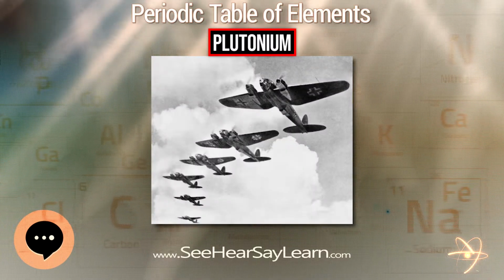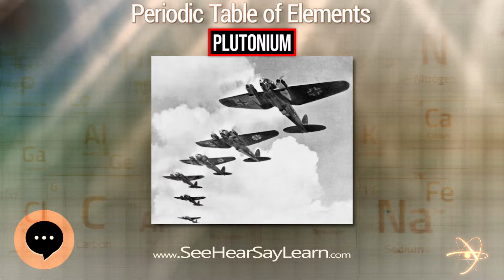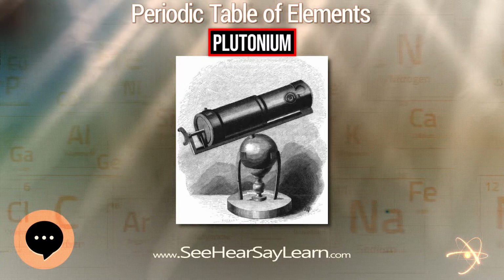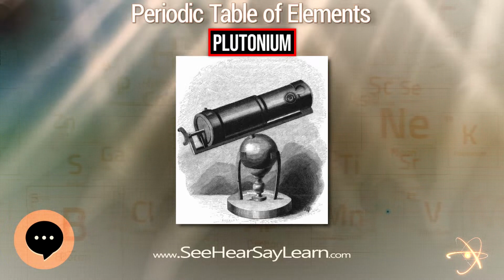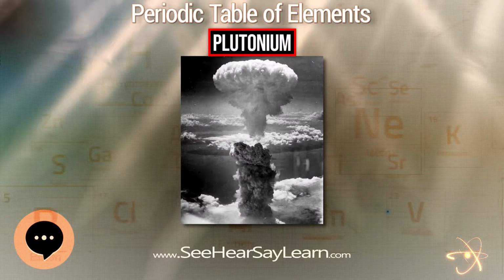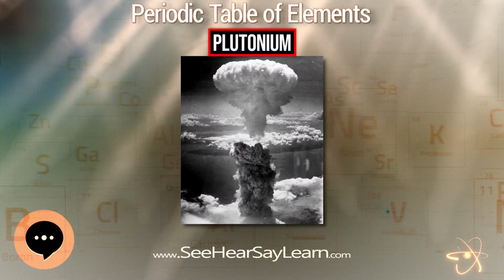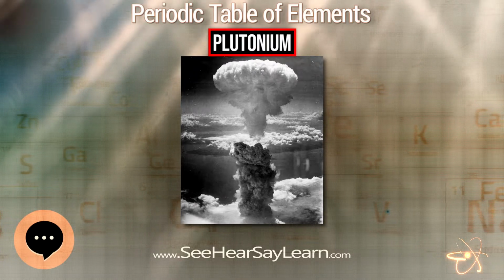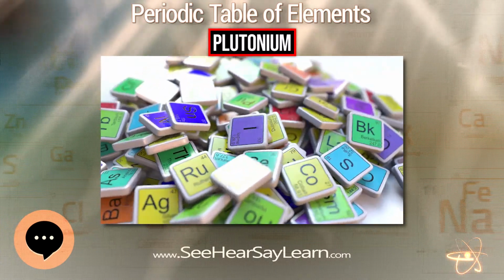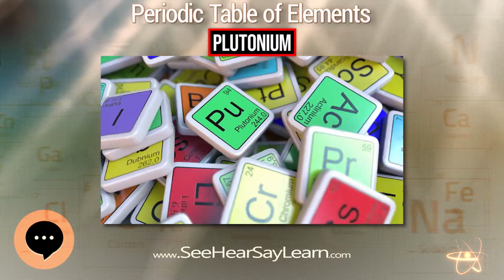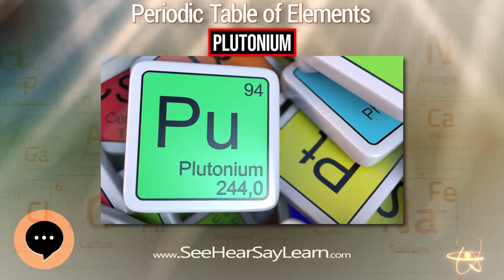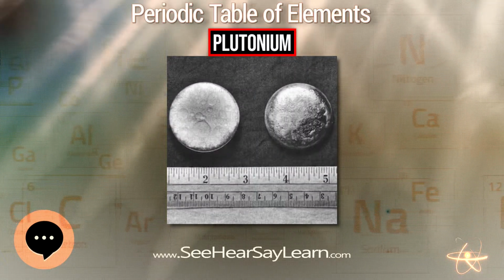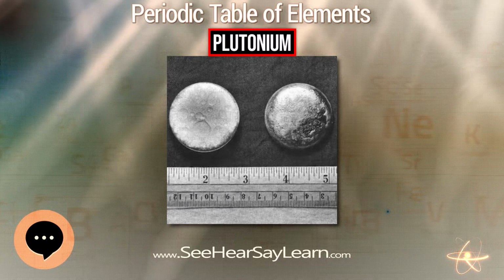Unlike most materials, plutonium increases in density when it melts, by 2.5%, but the liquid metal exhibits a linear decrease in density with temperature. Near the melting point, the liquid plutonium has very high viscosity and surface tension compared to other metals. Plutonium normally has 6 allotropes and forms a 7th at high temperature within a limited pressure range.